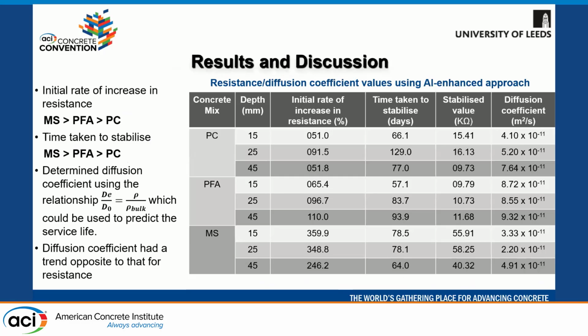So, results from the analysis. Resistance values were calculated using the AI-enhanced approach for all three concrete types at 3 different depths. Microsilica increased at a faster rate initially, followed by PFA and PC. Microsilica took more time to stabilize than PFA and PC. This is because the addition of supplementary cementitious material altered the pore structure. Also, microsilica is a denser material, leading to extensive increase in the resistance.